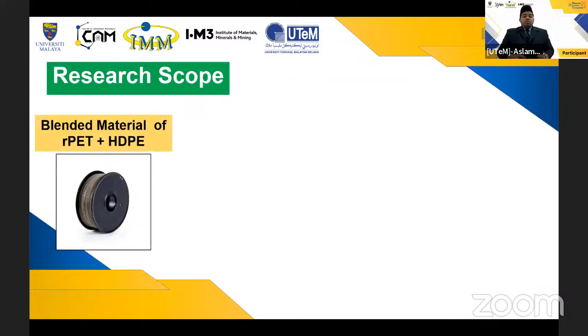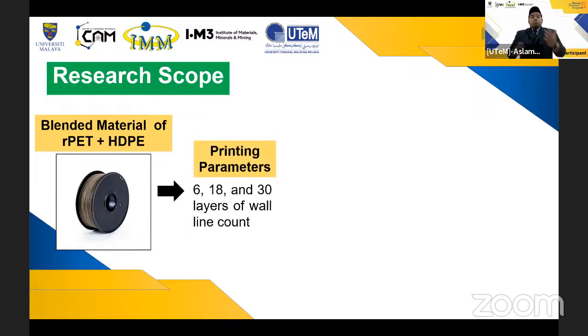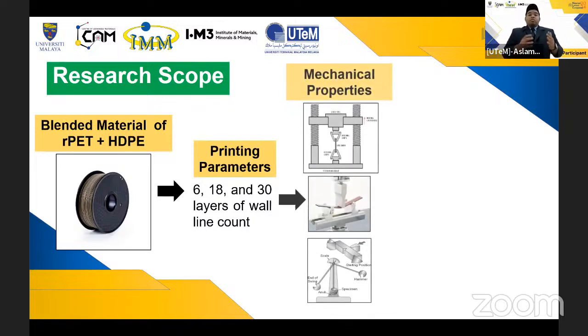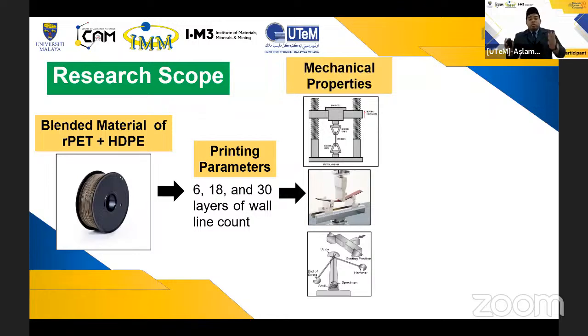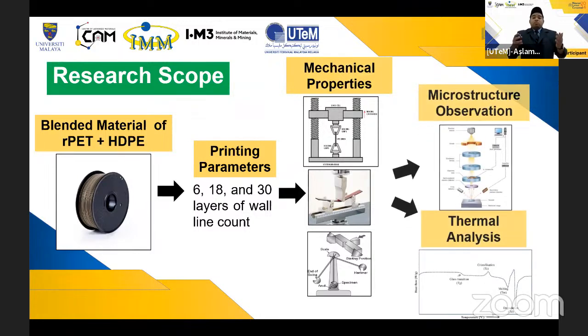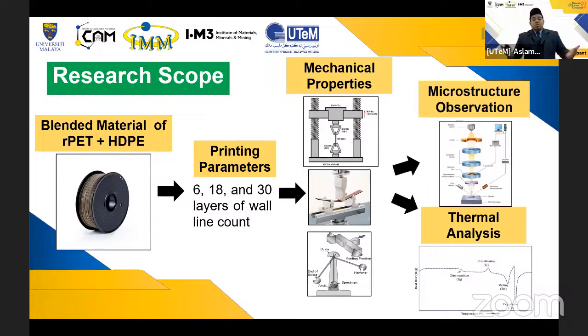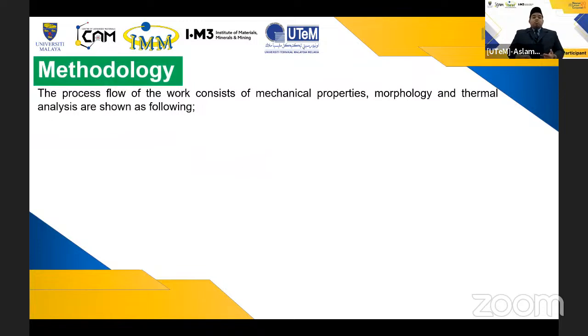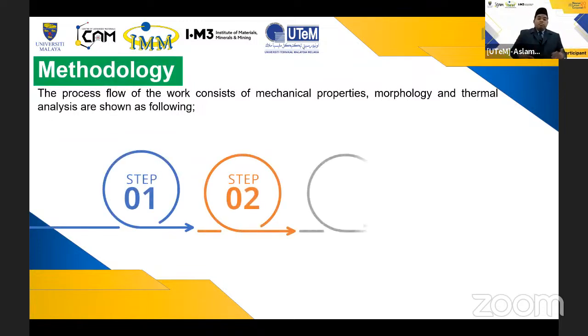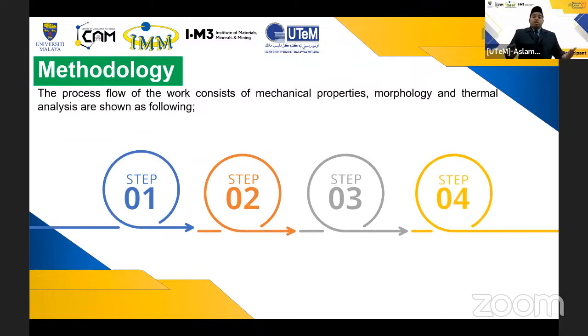So the scope of my research is to blend the rPET material with HDPE to create the 3D printing filament. We then proceed to 3D print samples with varying wall line counts of 6, 18, and 30 layers. The 3D printed samples proceed to mechanical property tests and microstructure observation, and thermal analysis is also conducted. Below shows the process workflow, consisting of mechanical properties, morphology, and thermal analysis.